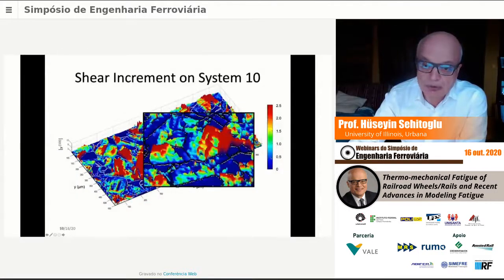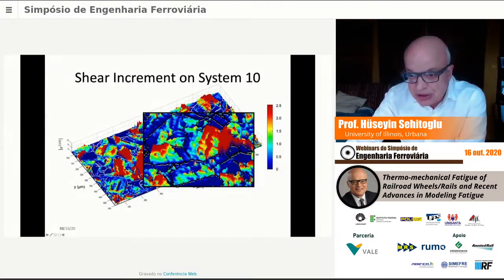So we proceeded to study these grain boundaries and how they affect the irreversibility. So this is a digital image correlation image we took on one of our samples. These are the grain boundaries. You could see here the strains in the slip bands here.